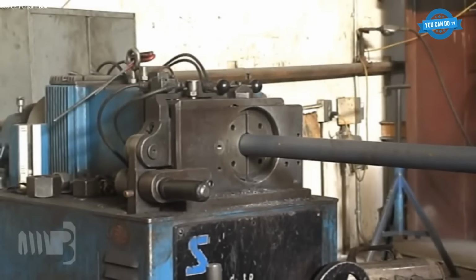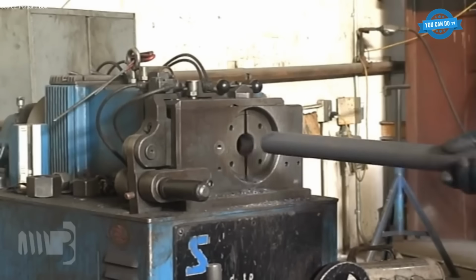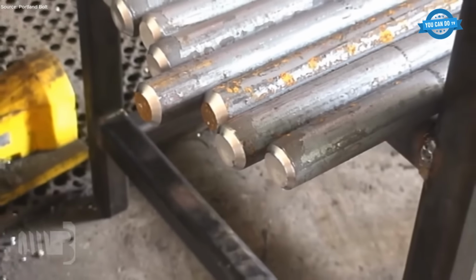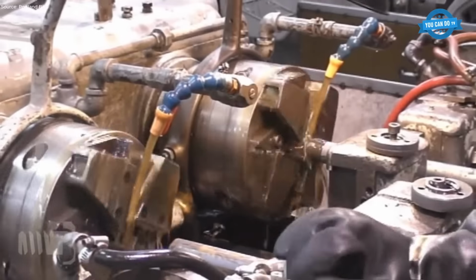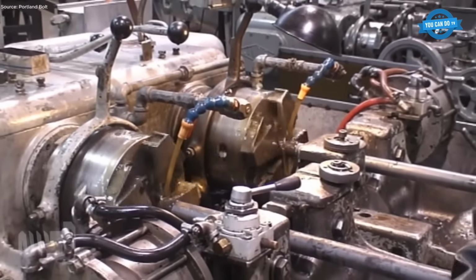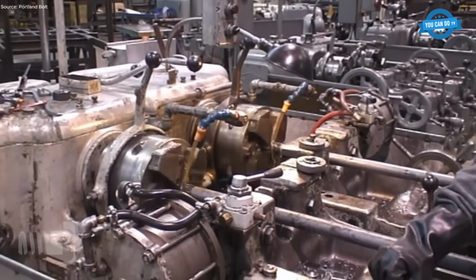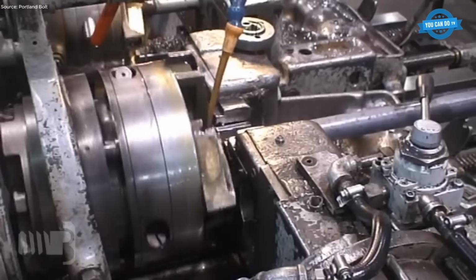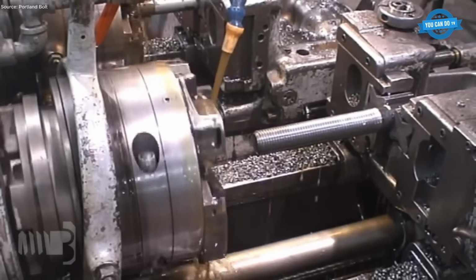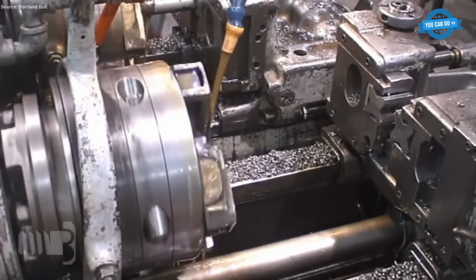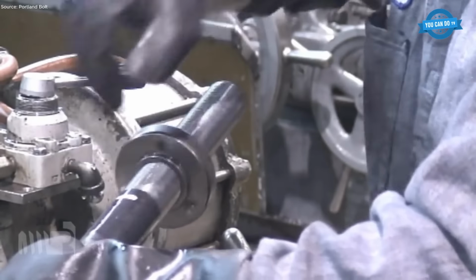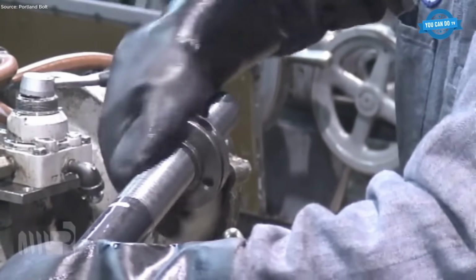Induction heating raises the steel temperature to approximately 2000 degrees Fahrenheit, after which a National upsetter forges the heated end into the hex shape. Threads are cut using Landis threading machines, with cutting oil applied to control heat and ensure dimensional accuracy. Threads are inspected using gauges to verify tolerance compliance.